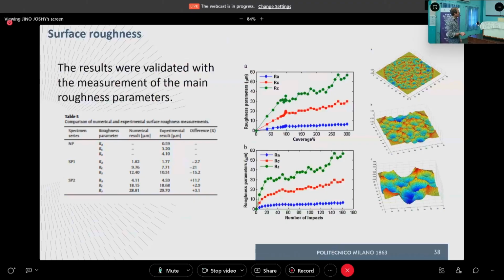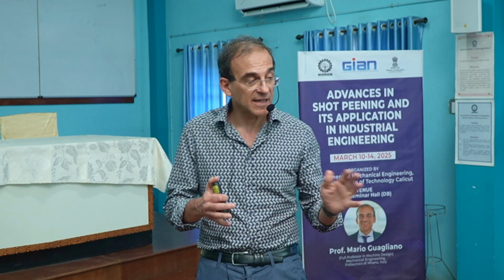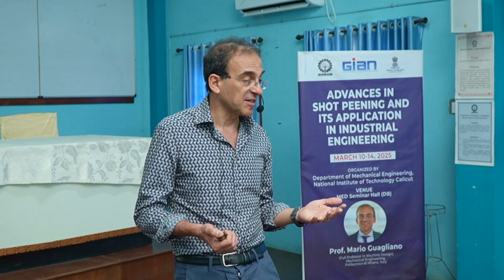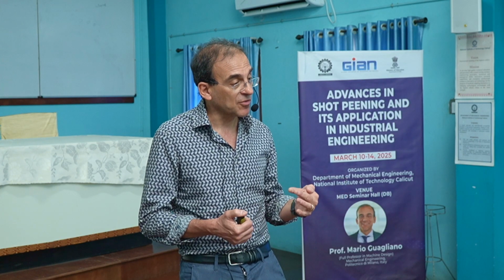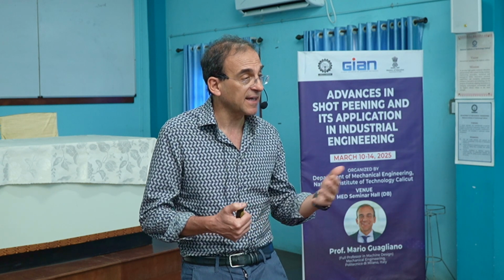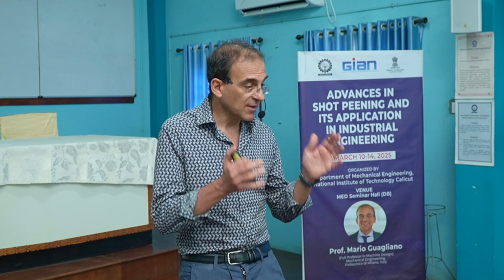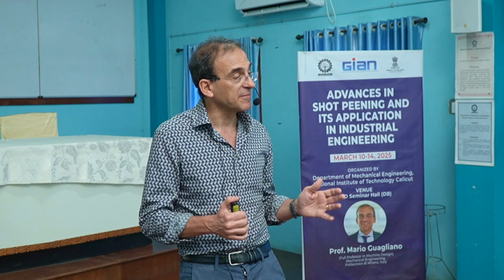And then finally we have compared what we have done with some experiments, obtaining an agreement that is sometimes good, sometimes not so good. Anyway, it's always confined between 10, 15, no more than 20%. And considering the difficulty in this kind of calculation, and that it is an estimation, this is enough. And this also can be used as an aid to correctly choose the final parameters of shot peening.